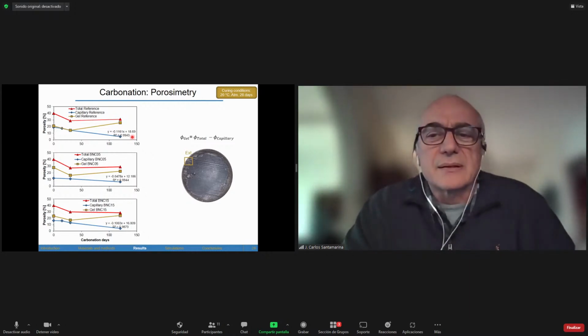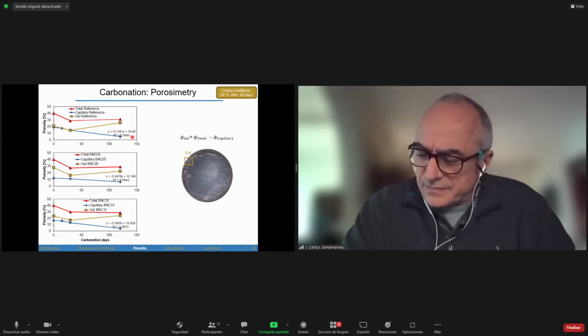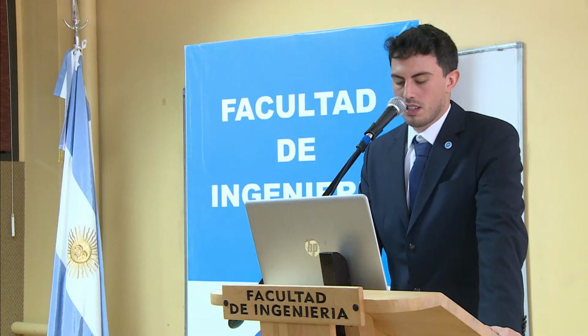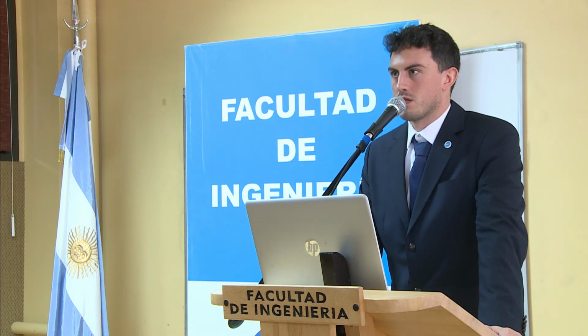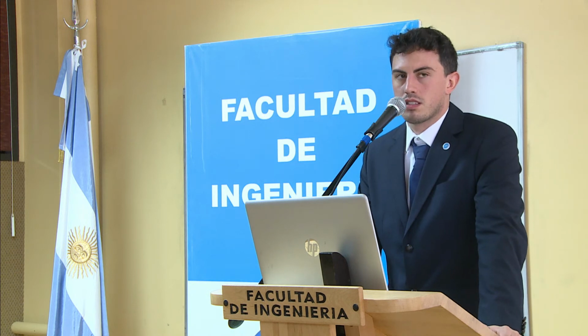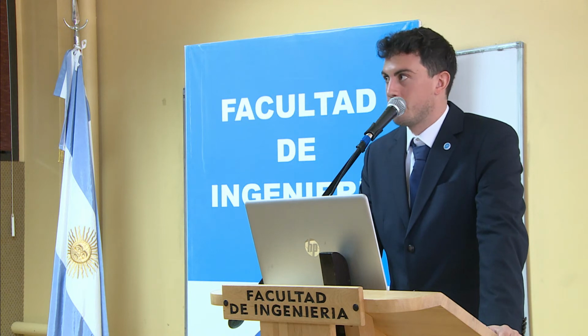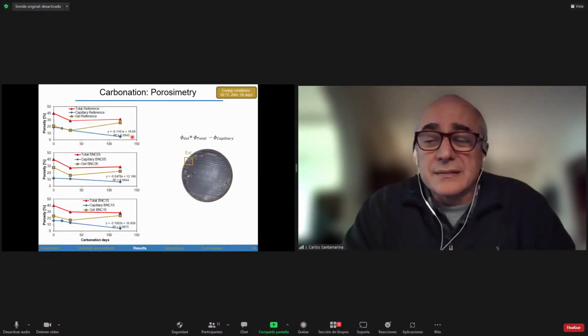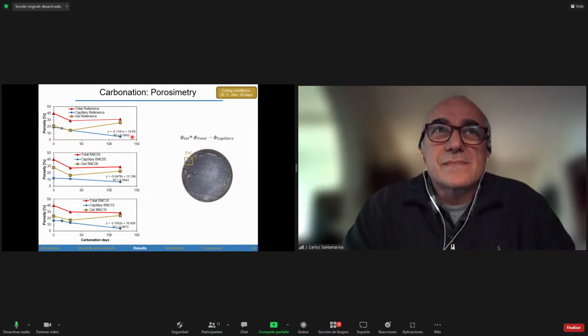What is so magical about 10 nanometers? Actually, we took that from the literature. I think for cement, it is considered that pores less than 10 nanometers are gel porosity, are gel pores. Does it make sense to you? Do you actually believe in that? Does it make sense that we want to make a difference? Well, it's an empirical reason, so we just work with that.